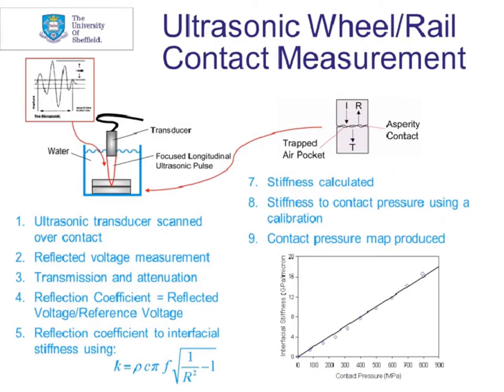So where do we start when we're trying to understand an interface? Well, the most important thing is to understand exactly what's going on in the interface. And as all tribologists know, it's actually very difficult in real time to measure what's going on inside a contact. It is very important that we do this because we need to know how friction and wear mechanisms actually evolve as an interface is happening, if you like. So you've got one element rolling against another or sliding against another. What's happening? We can look afterwards, obviously, to look at surfaces to see what's happened, but actually we need to know what's going on in the interface in real time.